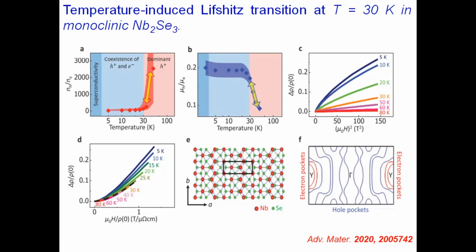So that means below 30K, a two band mechanism is present. That means the contribution from the hole as well as the electron pocket is finite. However, above 30K, there is a single band contribution. To be precise, above 30K only the hole is dominating, but below 30K, down to 5K, hole and electron both are dominating. That is why I told you, if a charge carrier is associated with multiple bands and multiple relaxation mechanisms, then they don't follow Kohler's rule, or they don't fall over one another. That is exactly what you can see here.